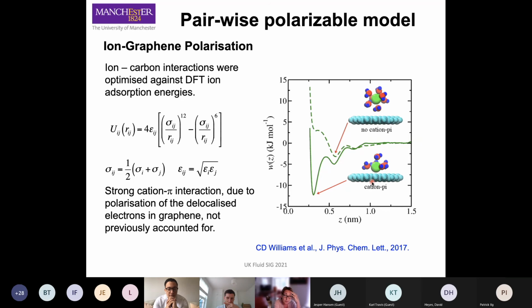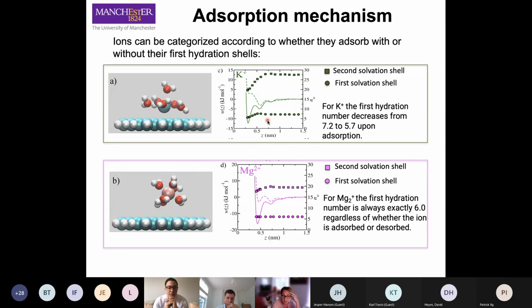Okay, so the idea was that in this way we had a very simple Lennard-Jones potential that can describe this polarizability effect. And then we ran molecular dynamics simulations for various ions at different concentrations, etc. And then what we saw is that the ions adsorbed, as we forced them to do, basically. But it was quite interesting because we realized that the arrangement of the water in the first solvation shell matters, because for the ion to adsorb, it has to dehydrate. So the fact that the ions were adsorbing or not was related not only to the hydration free energy and the size of the ions, but also to the way the water was rearranged in the first solvation shell.